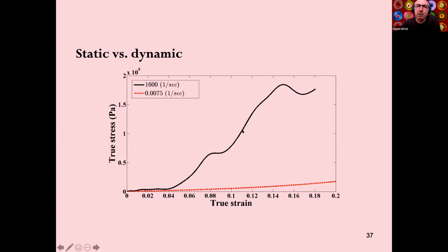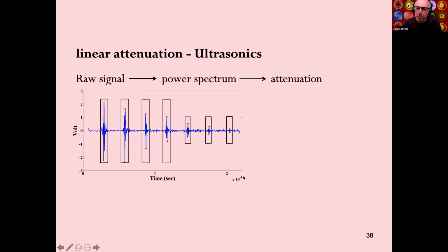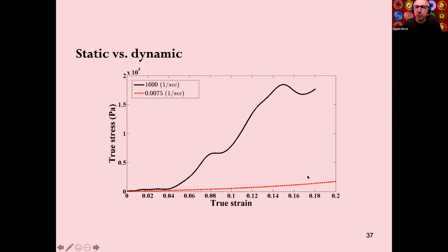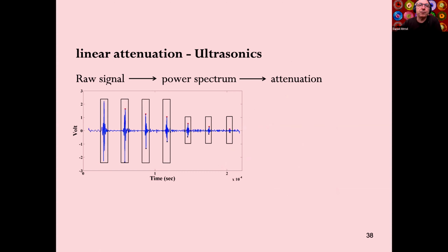The dynamic behavior, of course, is significantly better, higher, or stronger than the quasi-static, but it's also less ductile, and failure occurs at small strains, whereas under static loading you can go to very large deformations. So that's the plus and the minus. You have a stronger but less ductile material.